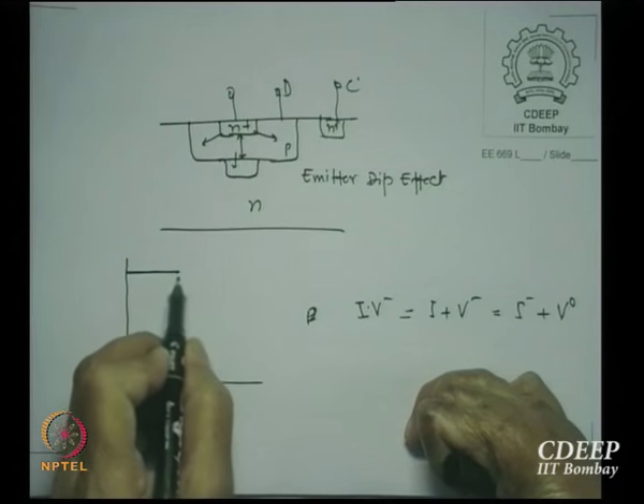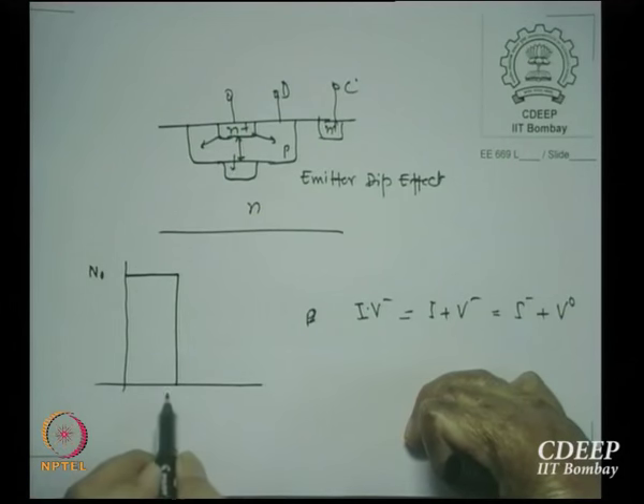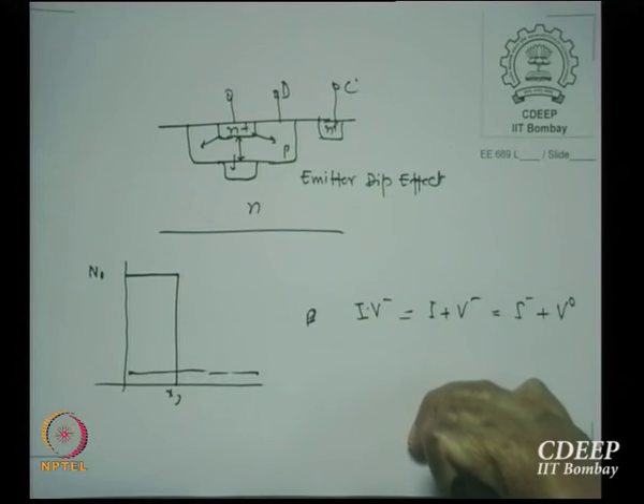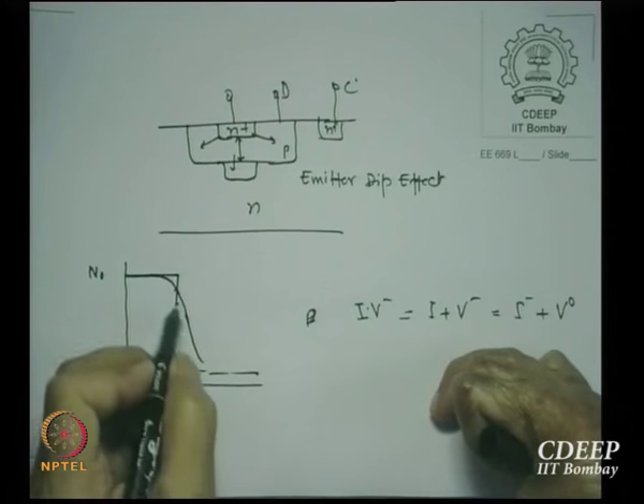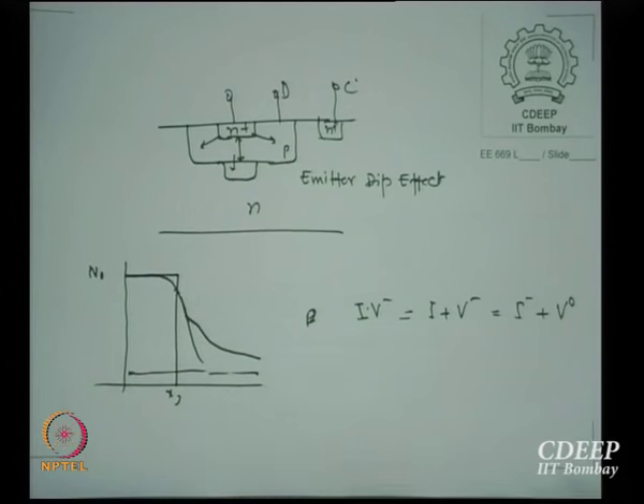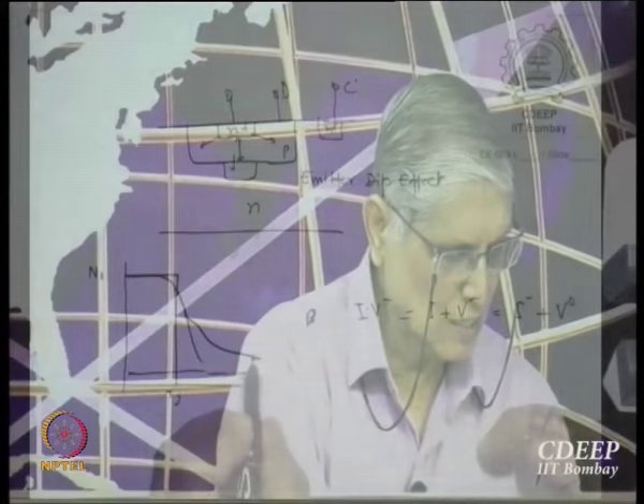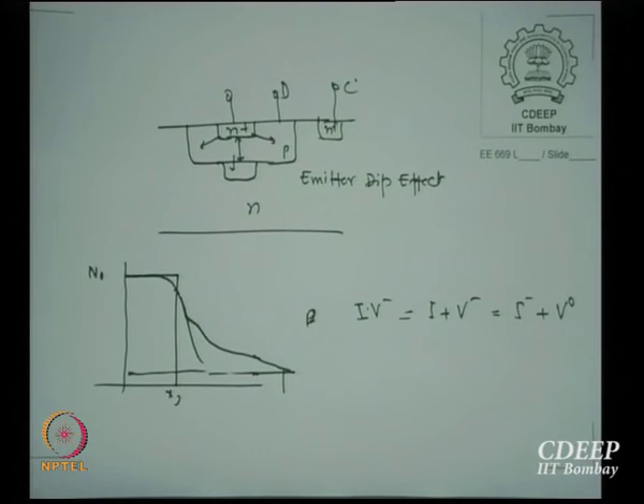In the case of phosphorus, there are many effects, but a major effect I can show you. Let us say this is the ideal profile I want for phosphorus, with surface concentration N0, and I want to create the junction Xj somewhere here. But what I figure out in real life is this profile, whether Gaussian or something like this. But in real life, the profile is not like this. There is a kink at some point and suddenly more impurities get out. The same reason one can ascribe: as the concentration of these impurities goes down below Ni, the vacancy pairs, both V minus minus as well as V minus, actually break down, they come out. And as more and more vacancies are available, phosphorus starts following these vacancies and goes more and more inside. So now the junction depth many times is orders higher than what you thought in your process.